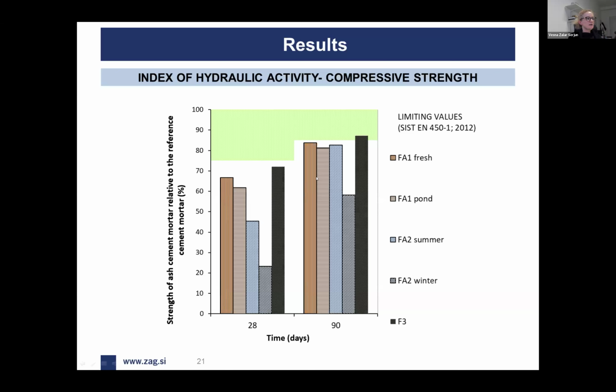FA ashes resulted in quite good results. This green line shows the limiting values measured after 28 and 90 days. You're measuring the strength of those mortars, and those are results of relative comparison to the references. In the cementitious systems, the ash which was so-called most promising till now, FA2 winter, is showing the lowest characteristics, and F3 again is the one which is basically the most promising for the cementitious systems, because after 90 days it reaches the limiting values.